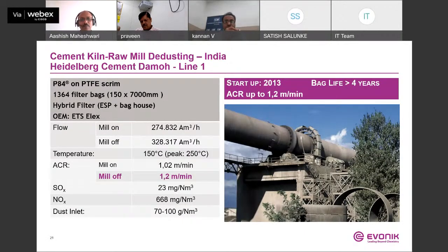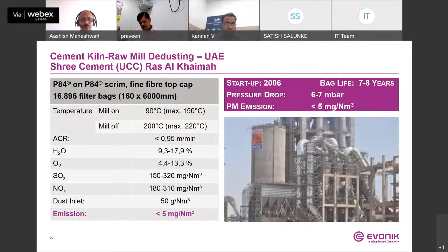This is another plant in Damoh, Heidelberg Cement, formerly. It started in 2013 and they changed the bags partially after 5 to 6 years. Overall, the bag performance is very good. This is one of the largest references, UCC Cement at Ras Al Khaimah. This plant started with P84 on P84 scrim with around 17,000 filter bags of 160 diameter and 6,000 millimeter length. Emissions are well below 5 mg. The bags have performed more than 8 years, so they changed them last year, and the installation is going on, again with P84.